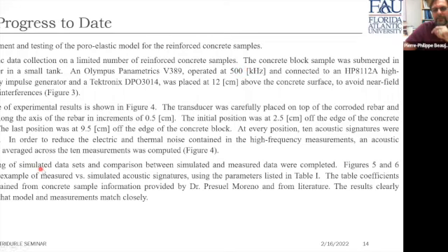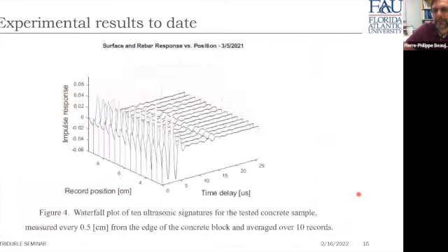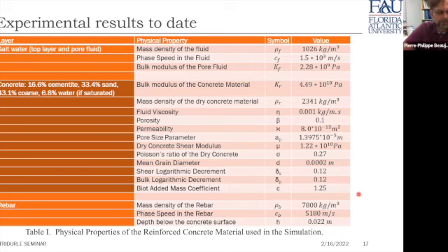Now, processing of simulated data sets and comparison between simulated and measured data were also completed. In figure 5 and 6, we show an example of measured versus simulated acoustic signature using the parameters listed in table 1. The table coefficients were obtained from concrete sample information provided by Dr. Presuel Moreno and from the literature. And the results really clearly indicate that the model and the measurements match closely. So here we are. Here's the set of parameters.